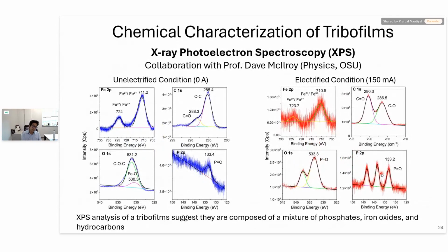This outcome was further corroborated by X-ray photoelectron spectroscopy, which also suggests the films are a mixture of iron phosphate, iron oxide, and hydrocarbons. So based on these results, we conclude that the application of electric field generates more tribofilm, and that is because it accelerates mechanochemical reactions. In the case of phosphonium phosphate additives under these conditions, we think that the reaction outcome is the same. The final composition of the films is more or less comparable, but it's the amount, or the yield, of tribofilm that is increased when the electric fields are applied. So the difference is more in kinetics rather than the reaction pathway itself.